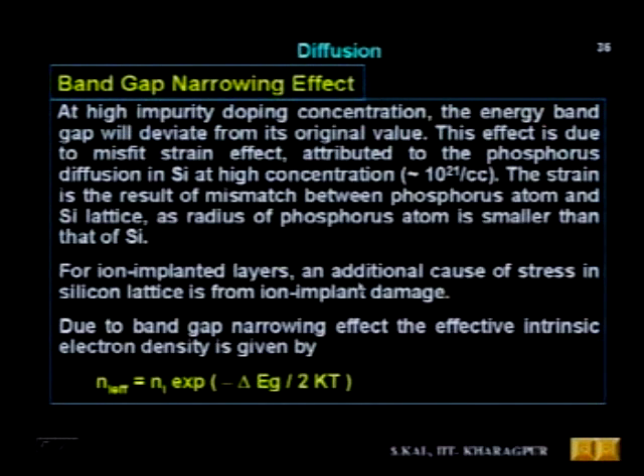Because of the strain and stress formation, the band gap will be narrowed, and that is given by this relation: ni effective is equal to ni exponential of minus delta Eg by 2kT. That means if delta Eg becomes smaller, that is, it is narrowed down, then ni effective will increase compared to ni, because it is an exponential with a negative sign. Okay. So because of this band gap narrowing, the effective doping concentration will also change. That is the ultimate effect of high concentration of phosphorus in silicon. This is known as the band gap narrowing effect. Okay.